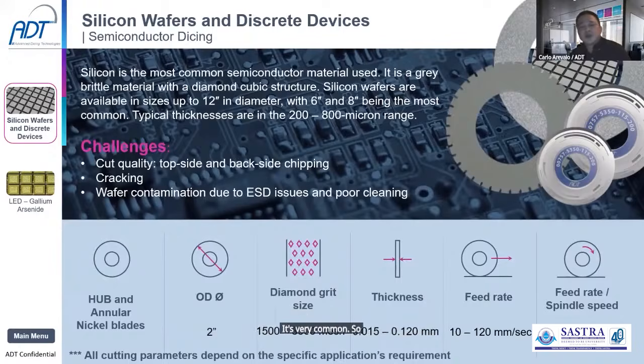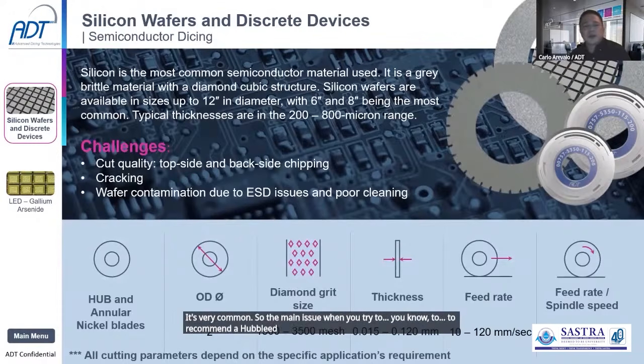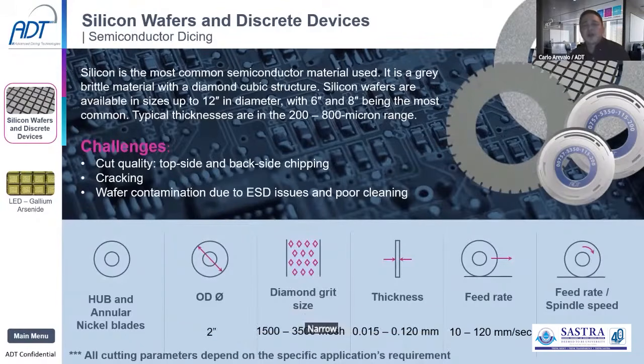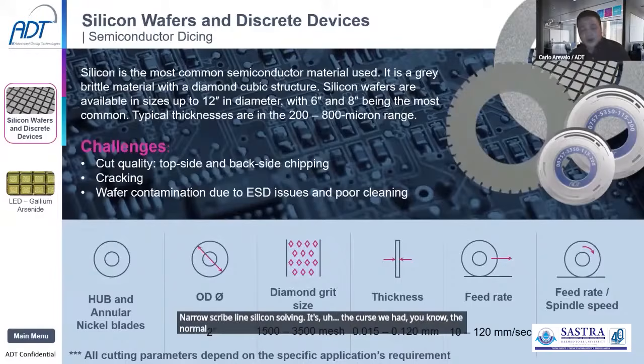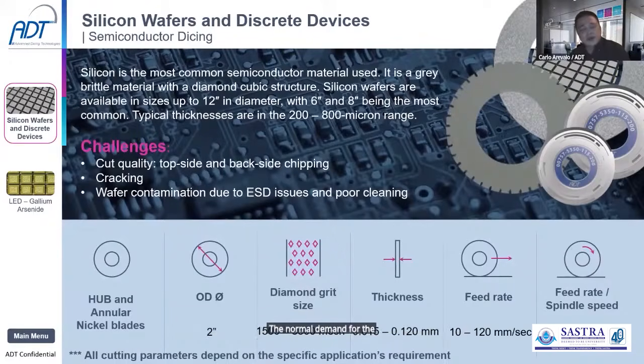So the main issue when you try to recommend a hub blade for a particular narrow scribe line silicon sawing is the kerf width. The normal demand for the kerf width now can go as small as 15 micron to 20 micron. So this kind of narrow scribe line is very challenging to deliver with a relatively passable amount of chipping, because chipping size is somehow relative to the grit sizes.